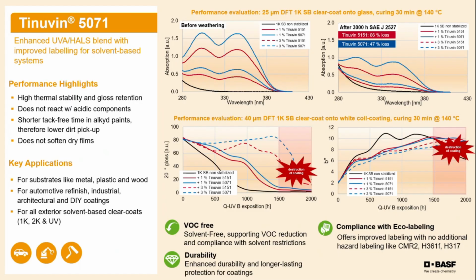Tinuvin 5071 is a UV absorber and HALS blend designed to improve the labeling for solvent-based coating systems. It provides high thermal stability, excellent gloss retention, and does not soften the dry films, which lowers dirt pickup over time. Key application areas are substrates like coatings over metal, plastic, or wood. Industries like automotive refinish or automotive OEM, industrial, architectural, DIY coatings. And as far as the type of solvent-based clear or pigmented system, it could be cured by either 1K, 2K, or UV curable systems.